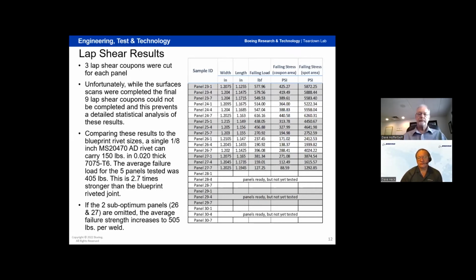So this is comparing to a MS20470AD rivet. So that's the aluminum rivets that are currently on these panels. They carry 150 loads in shear, 150 pounds of load in shear. And we were able, across the 5 panels we were able to test, we had 405 pounds of shear strength. And if we throw out a couple of those panels that didn't perform as well, we were able to increase that average up to 505 pounds per weld.